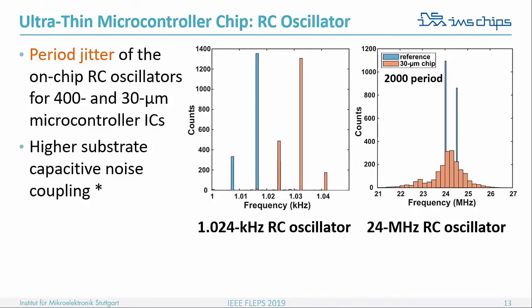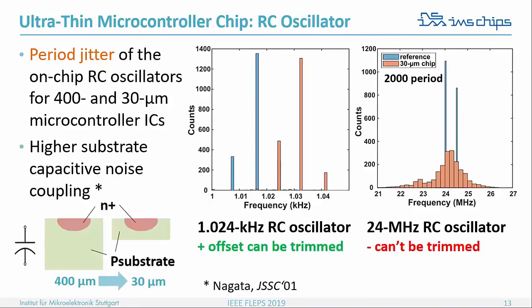However, for the RC oscillator, we find a degradation with a standard deviation and mean after thinning the chip, and that cannot be trimmed and needs a solution for that oscillator. Also from literature, we can see that from thinning down the chip, that might be the case in this high frequency noise. The capacitive coupling of the high frequency noise is more injected in the substrate in the thinned case.